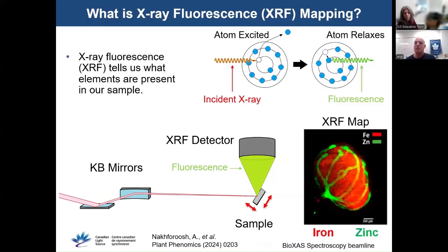So this is a 2D map of the iron and zinc contents in the root nodules of a soybean plant. These nodules have vasculature on the outside, almost like veins. And you can see the iron in red is pretty evenly distributed throughout the nodule, but the zinc in green is mainly in the vasculature on the outside.